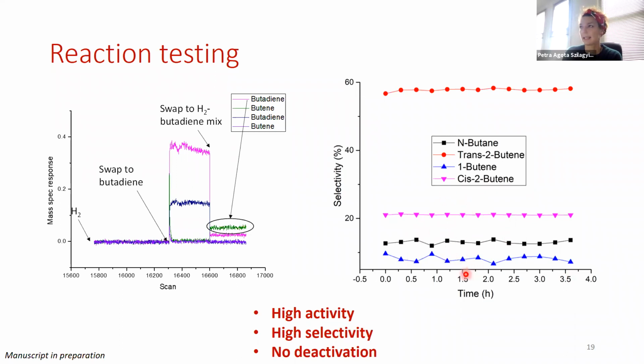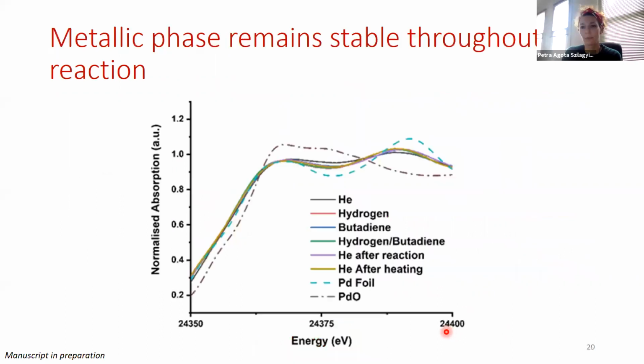So previous catalysts for this reaction, palladium catalysts that is, tended to deactivate in a much shorter space of time than this. And we could attribute this stability also to the palladium always being present in its metallic form, rather than forming any hydride or potentially oxide.